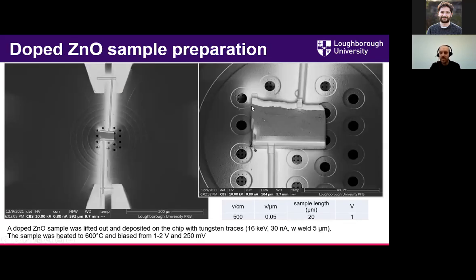And what we can do is make a ceramic sample. This is a zinc oxide sample that we've placed onto the hot stage, and then we've drawn biasing lines with our tungsten deposition. So we can heat the sample up and also apply a current and a voltage to the sample to cause it to sinter. In this case, we had zinc oxide, which we're going to heat to 600 degrees and then apply a current and voltage to it of around 1 to 2 volts and around 250 millivolts.